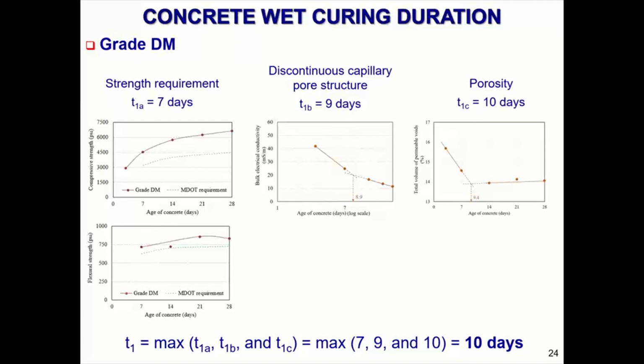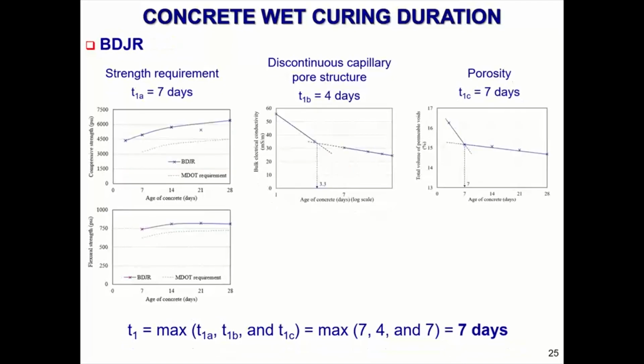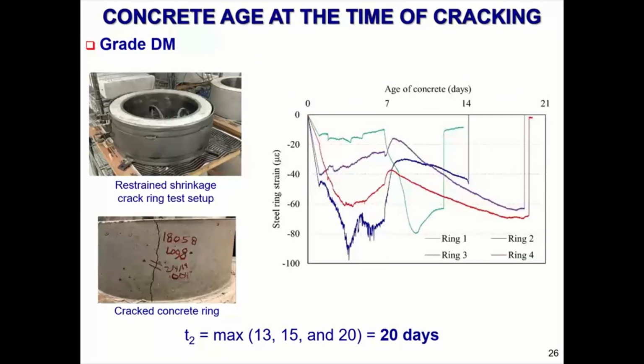This, as a side note, ended up pointing out to MDOT that we do not wet cure our grade DM concrete long enough to get the durability that we want. Right now, we only have a 7-day wet cure for our grade DM concrete. So that was just an added bonus of this research project. For the grade BDJR, you can see that for all 3 of those variables, the maximum amount of time was 7 days.